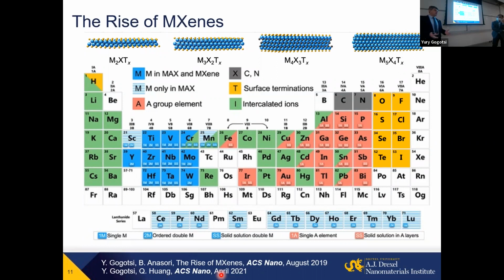For a number of electronic applications, people would love to be able to produce monolayer MXenes in their clean room by vapor deposition techniques. And people make ultrathin films, a few layers, a couple of nanometers, but there is no good controllable way to make wafer-size MXenes. But if you go back a decade or so, also very recently, no one was able to produce wafer-size graphene or molybdenum sulfide or boron nitride film. You just need to put effort into this and it becomes possible.